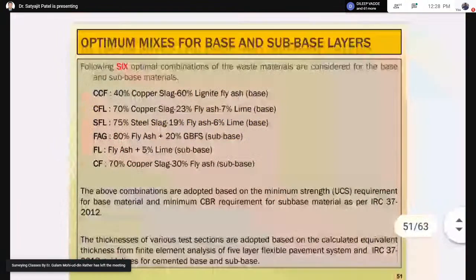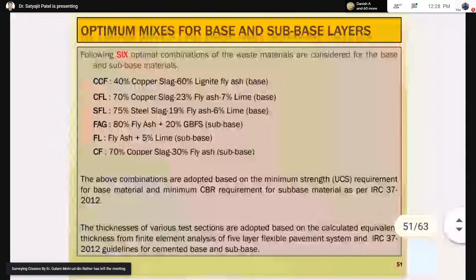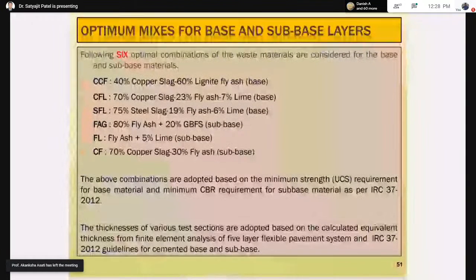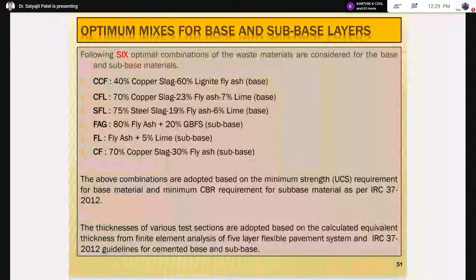Now, as a part of the DST project, we have used the optimum mix, based on the laboratory tests I have just explained. This mix has been selected as the optimum mix for use in the field. Instead of dolo lime, here we have used lime obtained from the market. That is copper slag, CCF copper slag and lignite fly ash, then copper slag fly ash lime, steel slag fly ash lime as base material, and in sub base fly ash GBFS, fly ash lime, and copper slag fly ash. So three base materials, three sub base materials have been taken. All these optimum combinations satisfy the requirement of IRC 37 as base and sub base material.